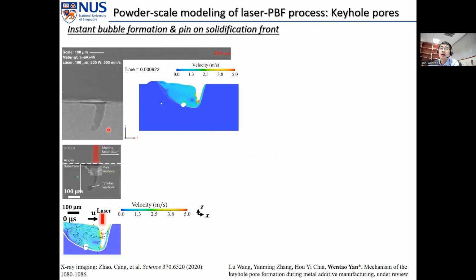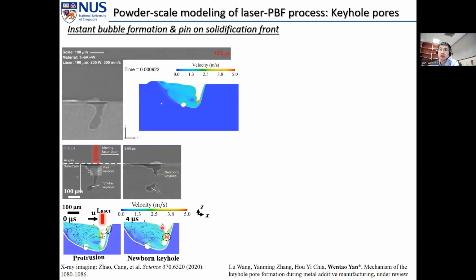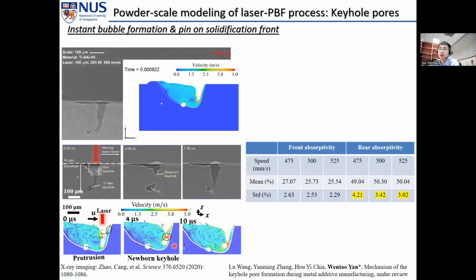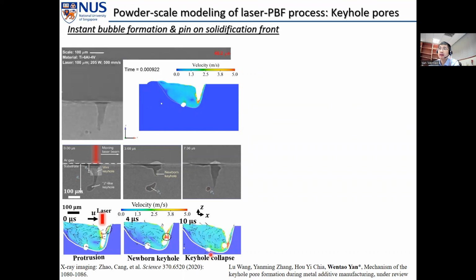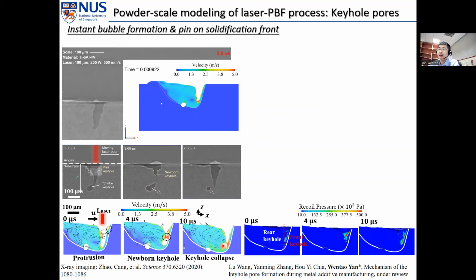In the X-ray imaging results by Argonne National Lab, they observed 3 different stages of keyhole pore formation, and our simulation exactly reproduces these 3 stages. The first stage is a protrusion process where a new keyhole, called the newborn keyhole, forms, and this newborn keyhole will close the previous keyhole. This part the laser cannot reach, so the energy will be reduced. So there will be a collapse. So it's keyhole collapse here, which then forms a keyhole pore.